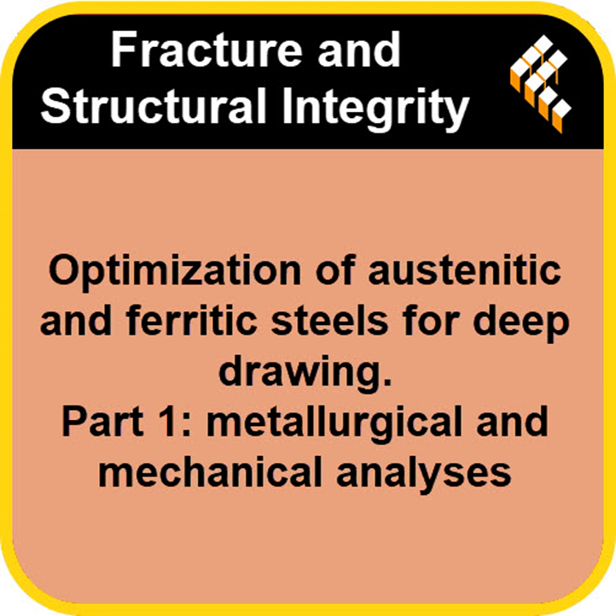How so? Well, first, the austenitic 304 showed massive work hardening, as expected. It got much, much harder in the deformed areas than the ferritic 430 did, up to 180 Vickers points harder. That's that strain hardening exponent we talked about. Exactly. Now, when that 304 was tested with lubrication, the hardness increased steadily as you measured towards the apex, reaching its absolute maximum value right at the apex, zone 10. Showing that the most deformation happened right where it should, at the deepest point of the draw.